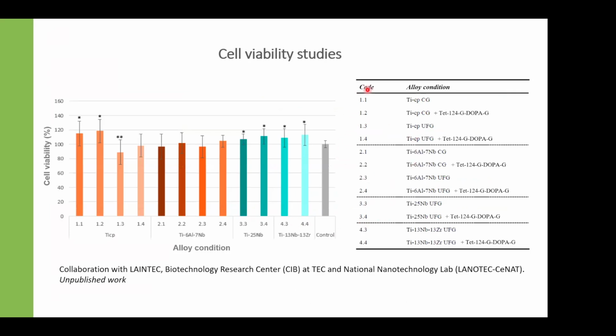Just as a showing how the cell viability goes, we tested a few of our coarse grain versus ultrafine grain HPT materials. We did some coating even with a peptide that's familiar to titanium surfaces. And in terms of the fine grain size, we do see a small improvement, but at least we are statistically equivalent in terms of cell viability. So some research works have shown that the cell viability, the integration of cellular tissue, protein adhesion, and then cell growth is improved when we use ultrafine-grained materials. We did see a little bit of improvement, but at least they are statistically equivalent.